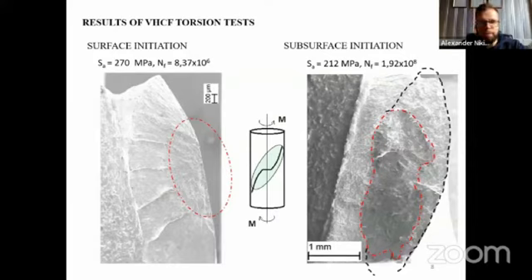If we look at the fracture surface, we can see that there are two types of cracks. The first crack starts from the surface, and we call it surface crack initiation. On the left, it's quite similar to classical high cycle fatigue with a manufacturer roof morphology. The second type of crack under very high cycle fatigue torsion loading is subsurface crack initiation. When we observed the crack initiation site, we did not find any non-metallic inclusions. So it's just a feature of the microstructure leading to subsurface crack initiation. As you can see, it's far from the surface, about 600 microns. This is quite unusual because the maximum torsional shear stress acts at the surface.